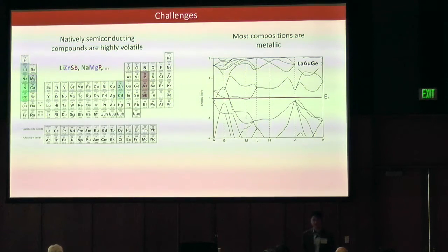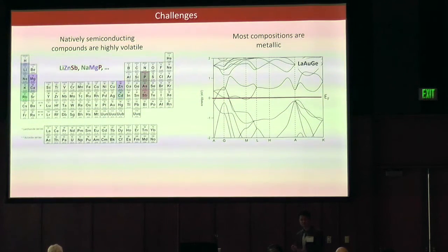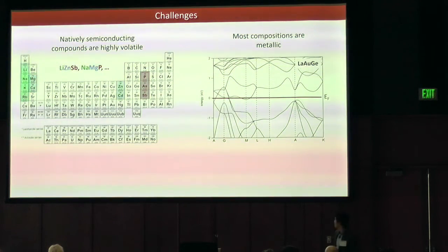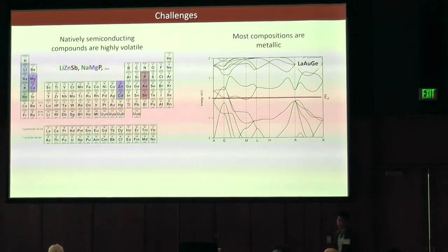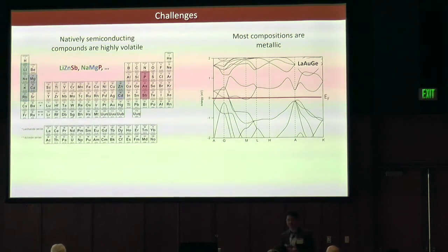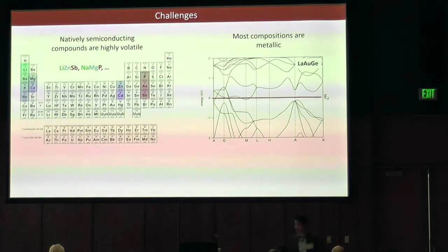These materials, of course, have a number of challenges. Despite the fact that hyperferroelectricity in this class was predicted almost 6 years ago now, ferroelectric switching in these ABCs hasn't even been demonstrated yet. One of the biggest challenges is that many of the natively semiconducting compounds are actually composed of very volatile elements. So from a material synthesis perspective, especially from a thin film synthesis perspective, this gives you lots of challenges, right?